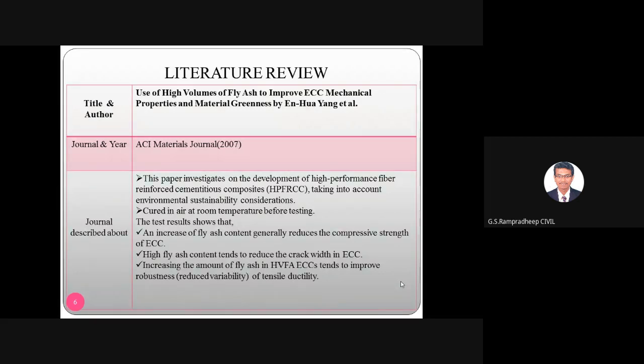When you are adding cementitious material like fly ash, fly ash will react with the calcium hydroxide as a secondary hydration. As a secondary hydration, over the running time of the concrete after setting, it again forms CSH. So the time gap is the reason that if you add fly ash, it takes a long time to get the strength, right? But in terms of sustainability, the addition of cementitious material will give a clear picture because it acts as a pore filler, because of the size of the particles. So if the pore filling effect is good, migration of contaminants will not be there. Automatically your environmental sustainability will be good.